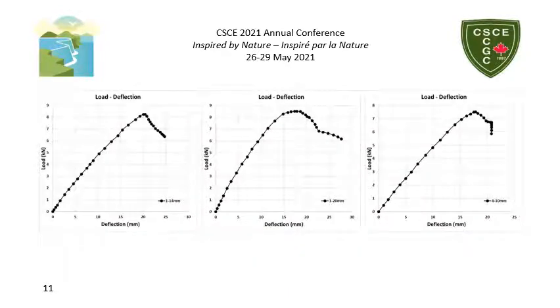With the test data, it is possible to plot load deflection curves for the different rebar configurations. The 20 mm rebar presented a steeper curve with some yielding plateau, whereas one 14 mm rebar and four 10 mm rebars presented very similar results, which shows that the number of rebars and their position, being one in the center versus one in each corner, are not relevant in this case. The tests were halted when the load dropped by more than 20% of the maximum value.